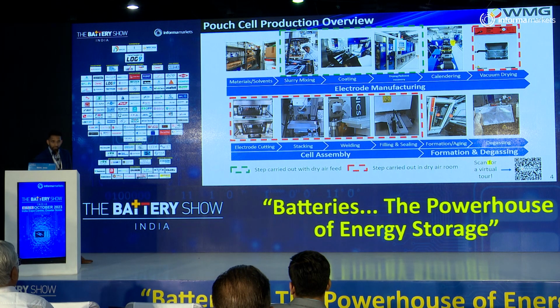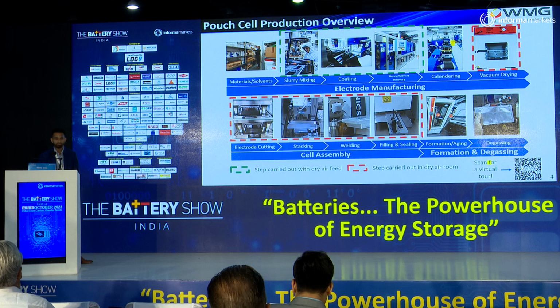Now, we are very well placed in our pilot line as we've modified our pilot line specifically to have a dry air feed. And a dry air feed is so important for battery material synthesis with especially high nickel content material, which is very moisture sensitive. So please do scan here if you would like a virtual tour of our laboratories. We also have a dry room facility, and I'm sure you've all seen some dry room capabilities and facilities that have been advertised at this trade show. And we have our very own provided by Munters.